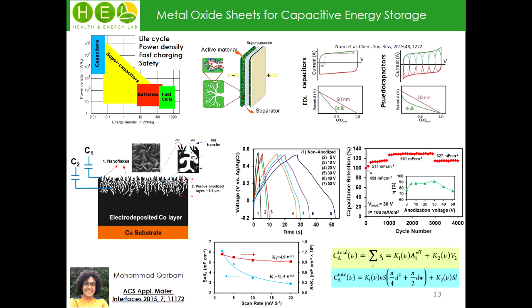The capacitance increased because all the porosities were accessible to the KOH electrolyte, and considering the stability of the system, we had good stability after nearly 4,000 cycles. Using a semi-empirical model, we tried to find the contribution portion of each part.